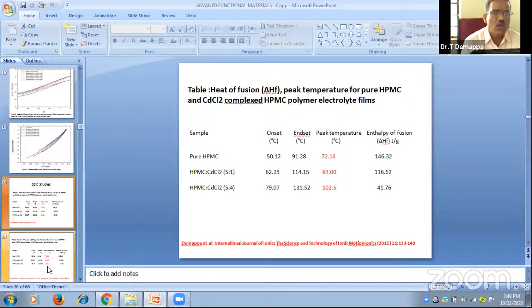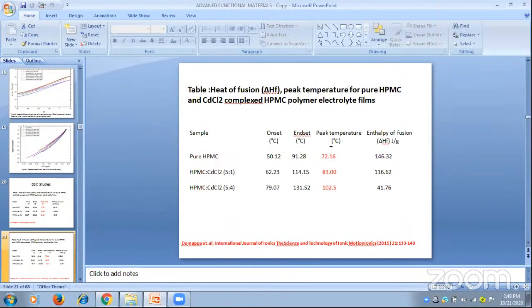I take one more inorganic salt with the same HPMC. You see cadmium chloride. You see pure HPMC 72.16, as in the previous one, because HPMC is fixed for this peak temperature or melting temperature. If you add 1% of cadmium chloride, you see 83 degrees centigrade. If you add 4% of cadmium chloride, the temperature stability increases tremendously.